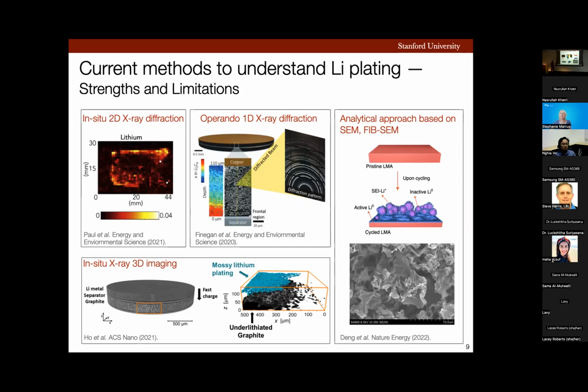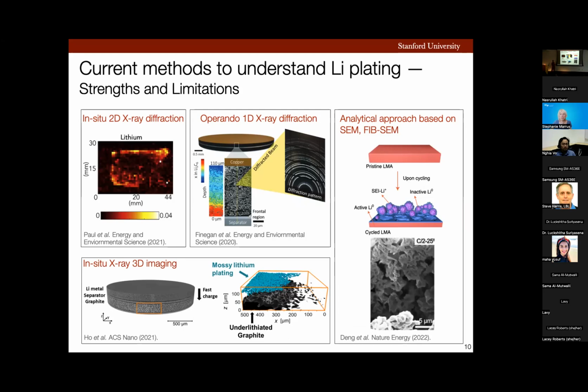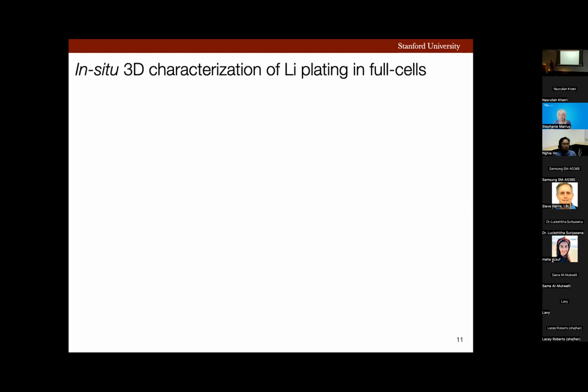This is an SEM image of a lithium dendrite. It does give us morphological information, as you can see, but this is only surface information. They were able to create these three-dimensional images using FibSEM, but we know that sample cross-sections for FibSEM are obtained through destructive ion milling. Thus, in situ three-dimensional characterization of lithium plating in full-cell lithium-ion batteries has been missing from literature.